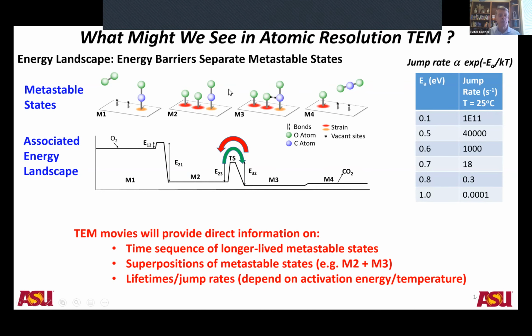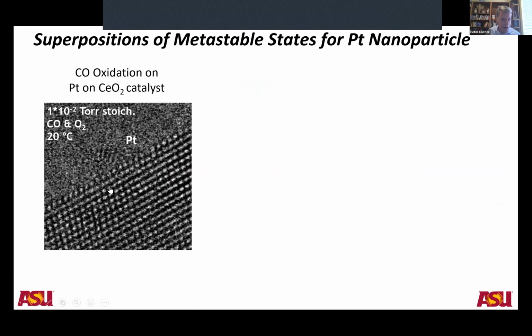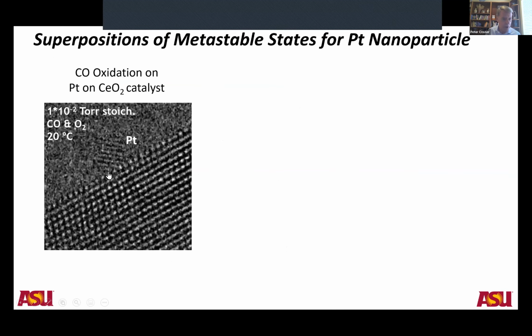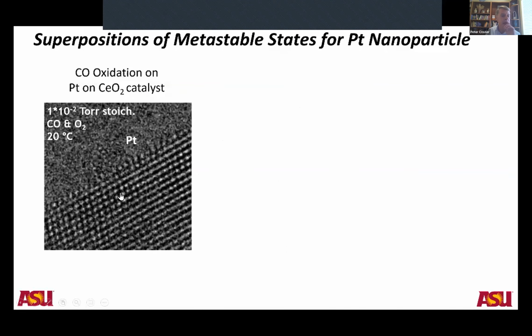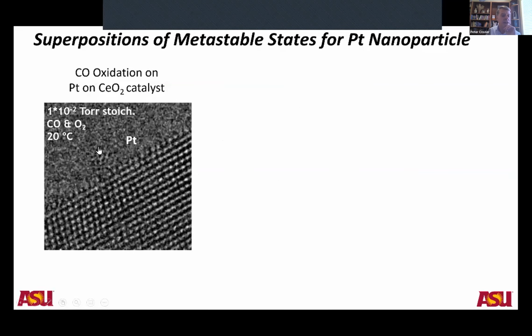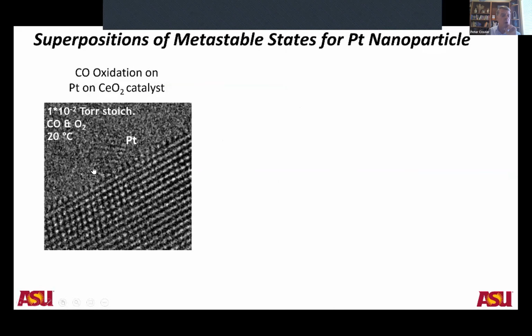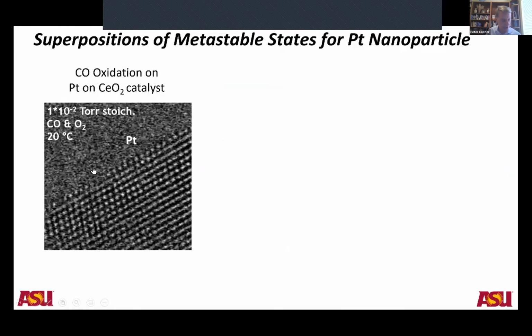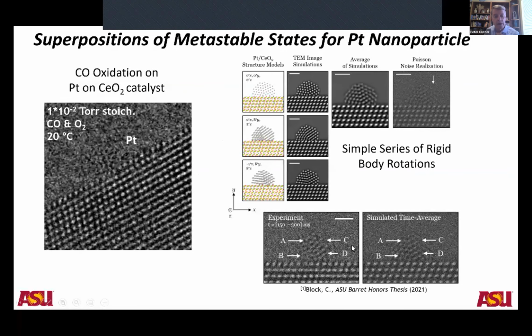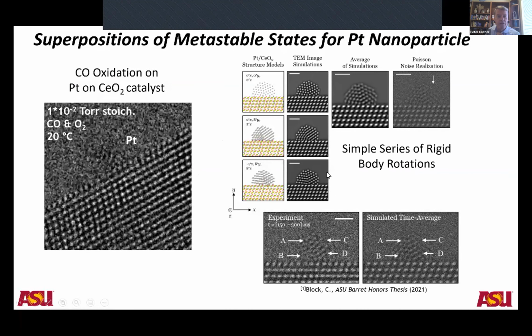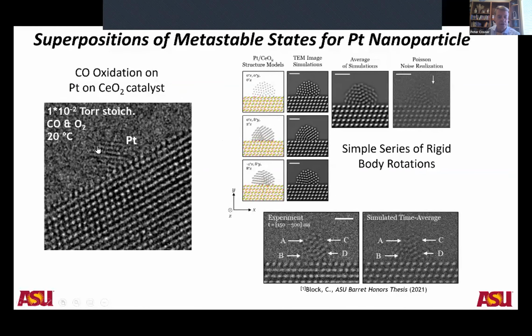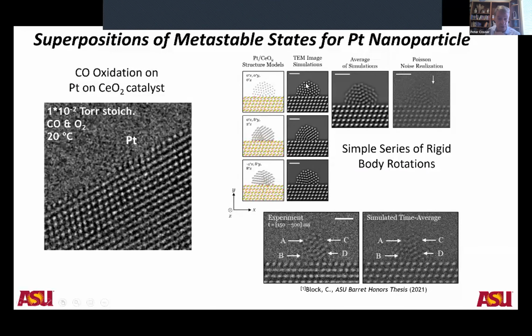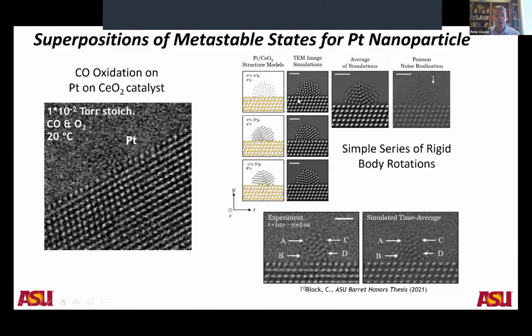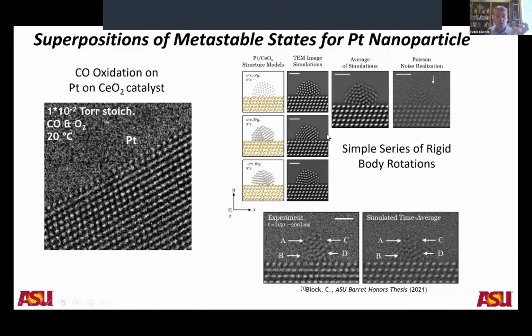So now if we think about structural dynamics or what we call fluxionality in terms of transitions between metastable states, and that the TEM image is going to show us the longer lived states or superpositions of states, we can go back to this platinum nanoparticle that I showed you early on and say, well, can we interpret this movie in terms of a superposition of different structures? And we had a clever undergraduate in the group at the time, Claire Block, and she was very interested in investigating this. And so we gave her some of the simpler frames from this movie, some of which you can see the evidence for a twin plane. And what Claire did was she simply went through a series of rigid body rotations.